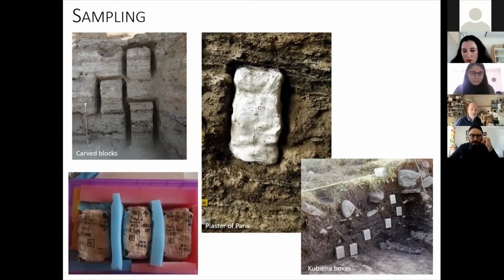Stabilizing the block sample with plaster of Paris, a plastic container, or even a Tetra brick is a common technique as well, with these materials being easily available in most countries. The only observation I have about plaster of Paris is that it can take some time to dry out, from several hours to a day, day and a half. So it might be tricky to use in wet climates.